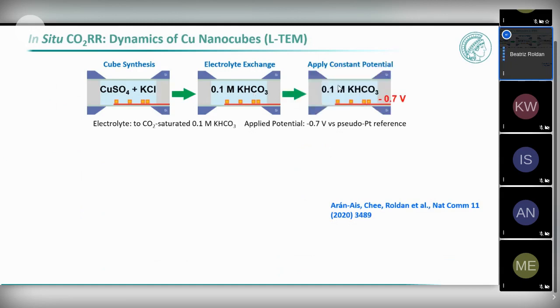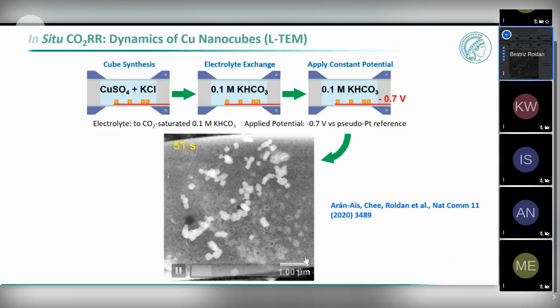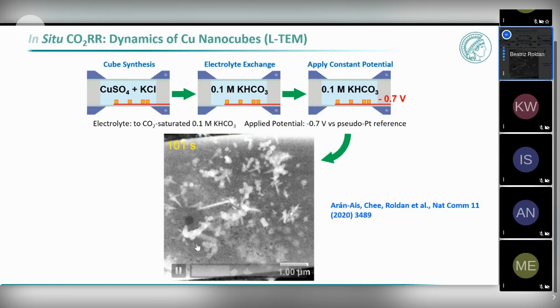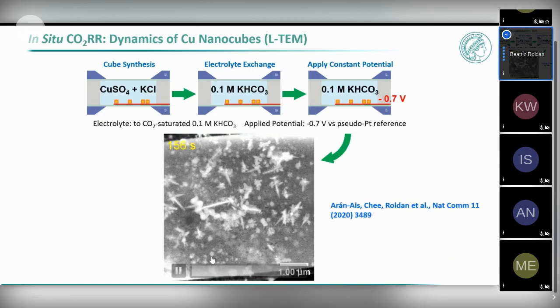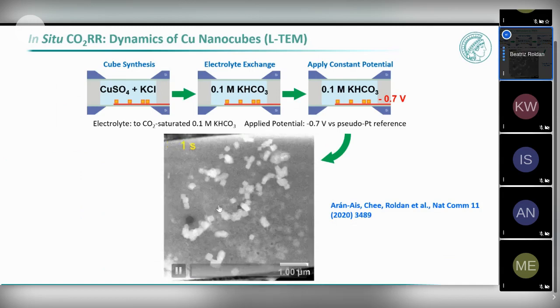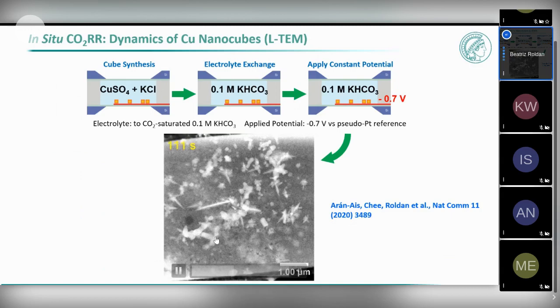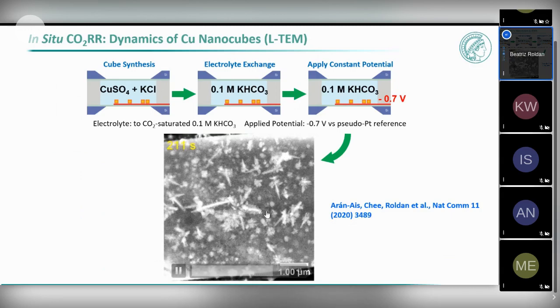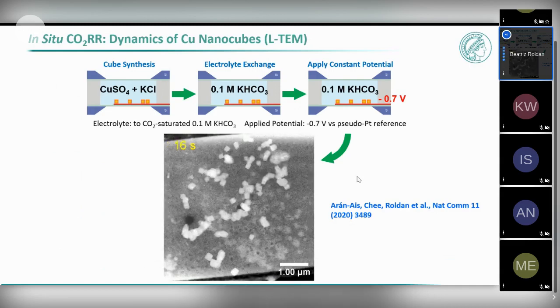And then I'm going to apply the negative potential, and I'm going to see what happens to my initially beautiful cubes. If you see here the data, you see first the mobility of the cubes. You see small particles being formed, so the cubes become unstable, they break up. We see dendrite formation: mobility, breaking up of the cubes, the formation of smaller particles, and then these dendrites. And as I told you before, the selectivity is very strongly dependent on the structure of the catalyst.